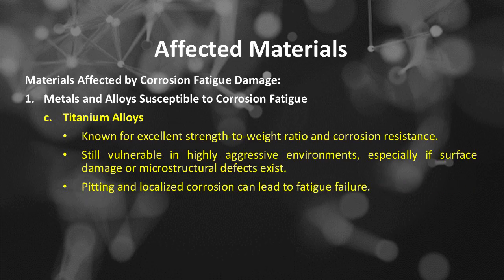Metals and alloys susceptible to corrosion fatigue. Number C is titanium alloys, known for excellent strength-to-weight ratio and corrosion resistance, still vulnerable in highly aggressive environments, especially if surface damage or microstructural defects exist. Pitting and localized corrosion can lead to fatigue failure.